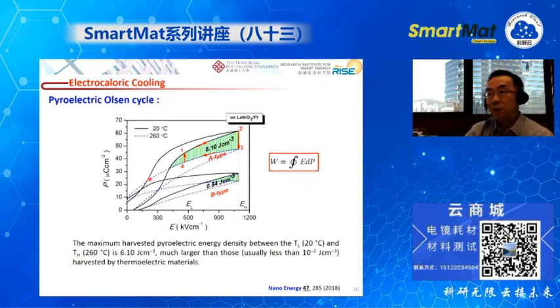We measure two different hysteresis loops. One is the black one at the low temperature, another is the blue one at the higher temperature. Then we can see if we build the Olsen cycle as indicated by this red arrow, we can actually get a work output which is equivalent to the area of this shaded part. The maximum achievable work output is around 6.10 joule per cubic centimeter. And if you compare this result to those thermoelectric materials which work in a similar temperature range, you can see the energy release is much higher than those thermoelectric materials.